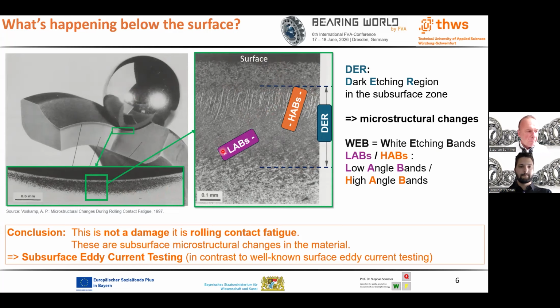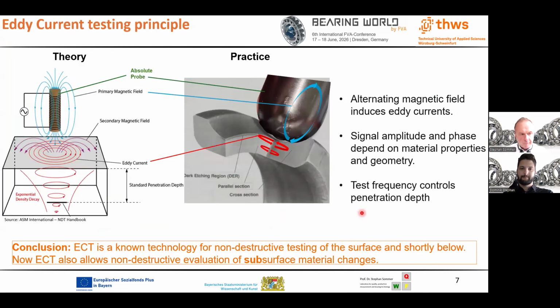So not to mix up with white etching cracks. Yeah, this is a completely different story. This is not a damage, it's fatigue. So that's the conclusion. Fatigue is not a damage. Fatigue is microstructural changes in the material, and we can measure it with subsurface eddy current testing in contrast to the well-known surface eddy current testing.